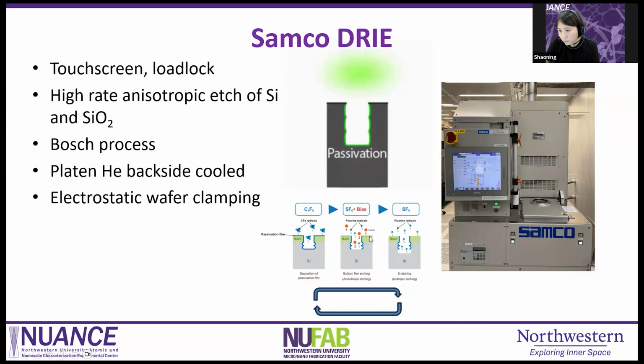So it will first remove the polymer on the flat surface, including the bottom of the trench. And once the thin polymer on the flat surface is removed, it will go on to the etch of the silicon. The side will stay coated with the polymer. It will remove a little bit, but not all, because the ion direction is mostly parallel to it. So this is a licensed process called the Bosch process, which is the particular name for this kind of vertical etching.